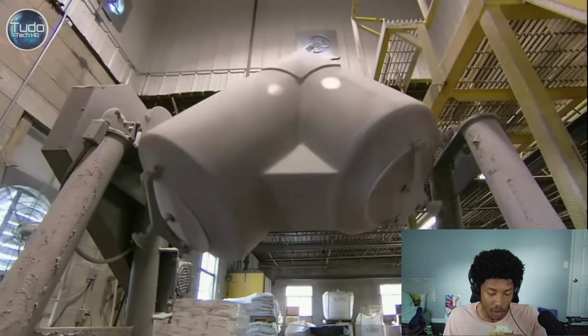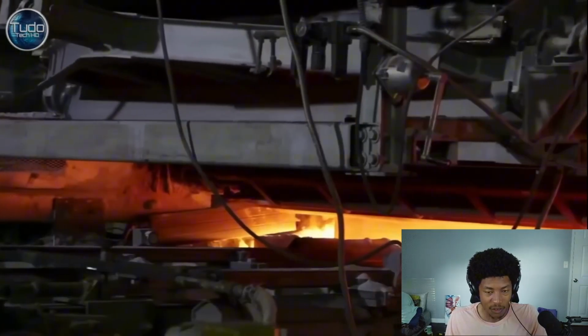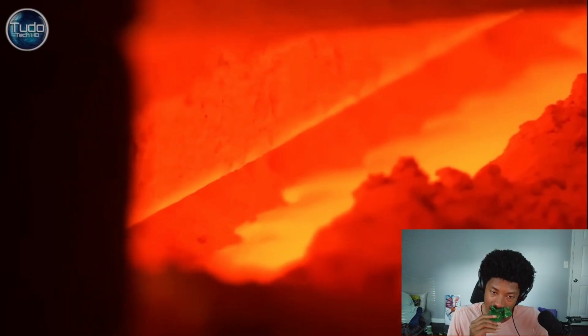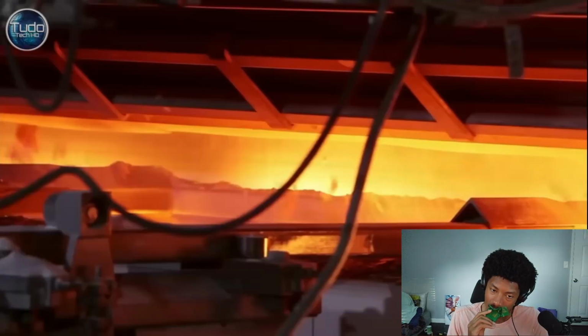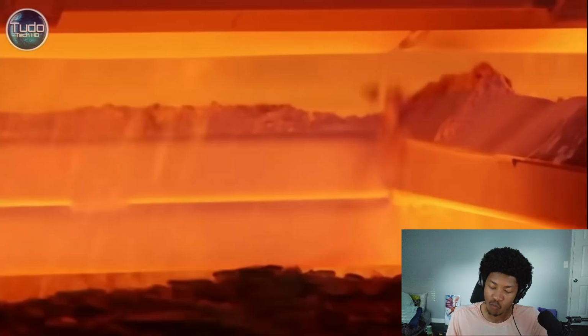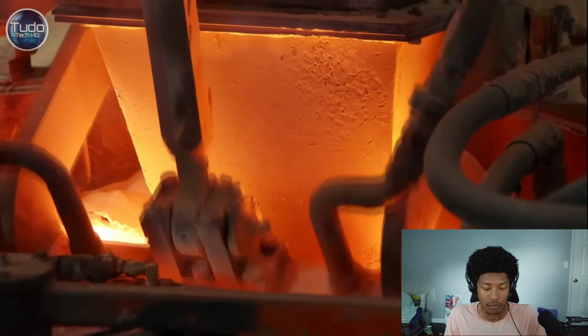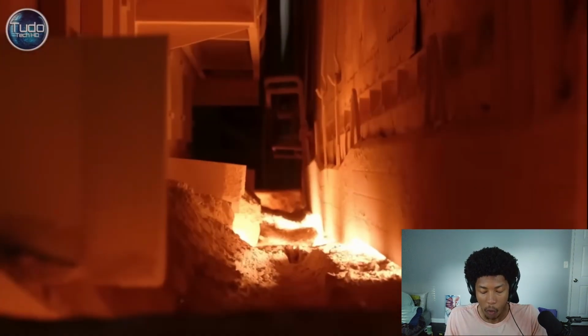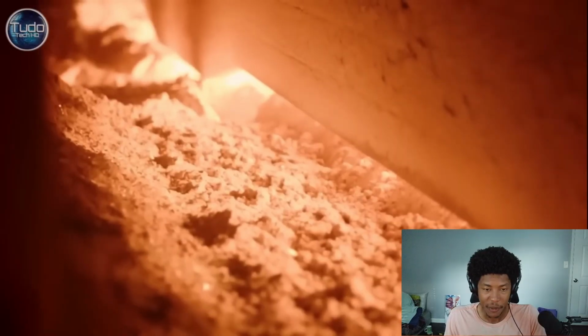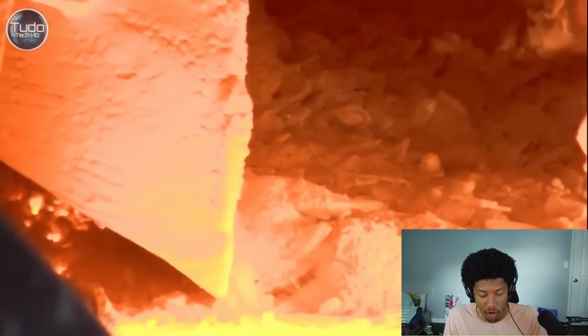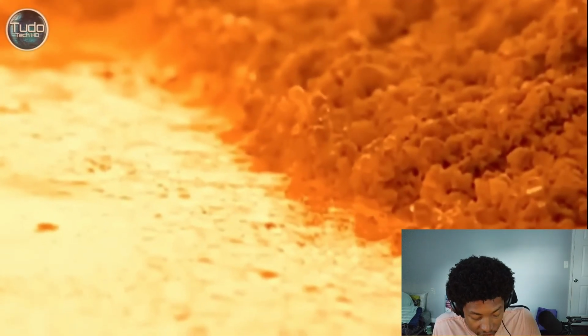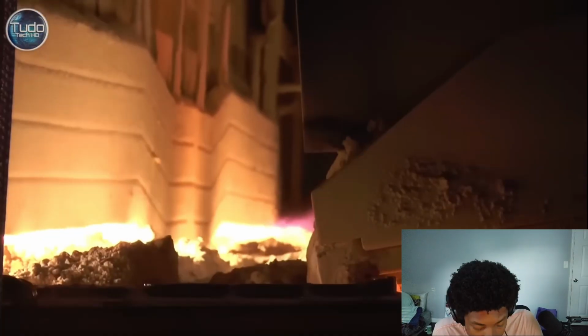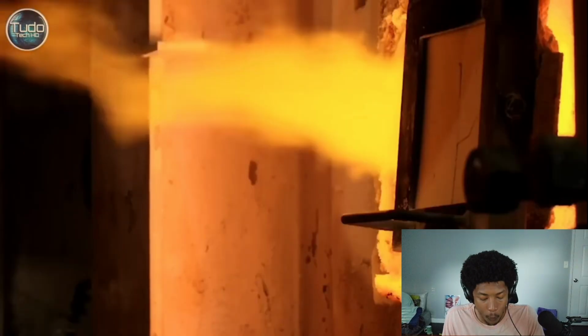This mixture, once ready, is continuously fed into the melting furnace, where it is transformed into liquid glass. This large, continuous kiln, made of refractory bricks, can operate 24 hours a day for 10 to 15 years without shutting down. The mixture enters from one side and is gradually heated until it reaches temperatures between 1,400 and 1,600 degrees Celsius. Inside the kiln, heating is typically done using natural gas. The ingredients melt, releasing gases and forming a homogeneous liquid mass. The liquid glass passes through a hotter zone to eliminate bubbles and impurities.